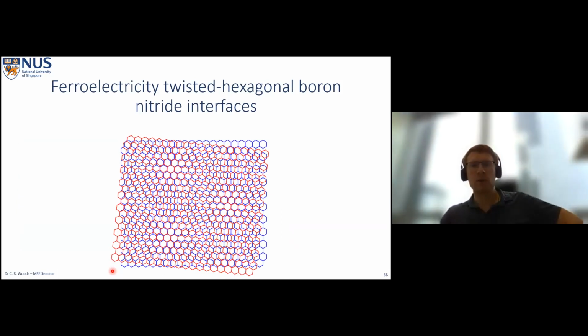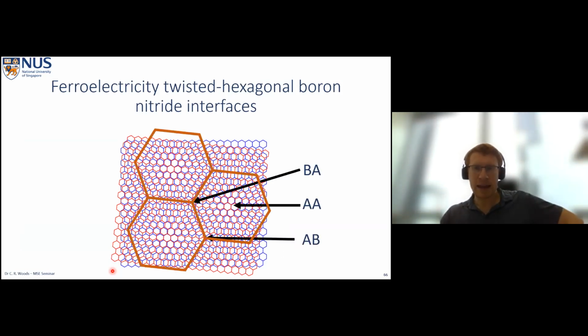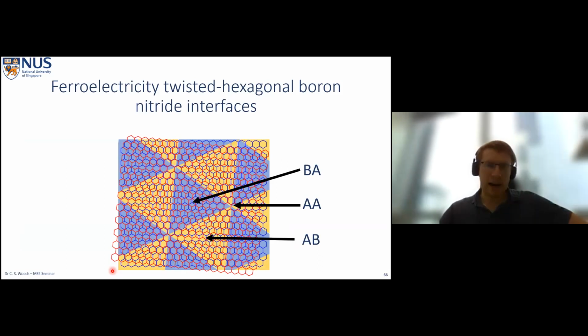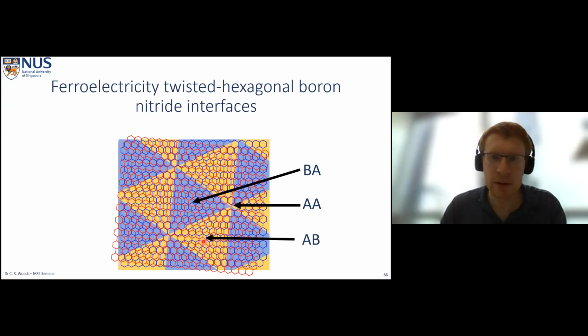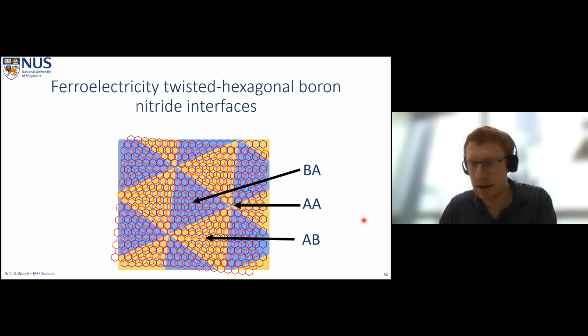And so we can return to our little schematic here. We have a superlattice where we see AA, BA, and AB. And if we overlap what our triangles would be, essentially our triangles would look like the BA and AB configurations, and the AA stacking, which remember for parallel is very energetically unfavorable. This becomes a small area of our superlattice area, and the BA and AB take up larger areas, and in fact equivalent areas to each other because they have the same energy.